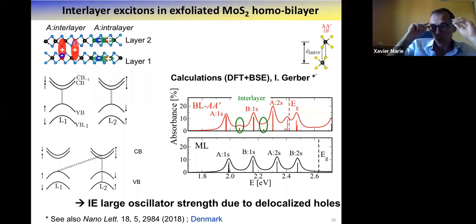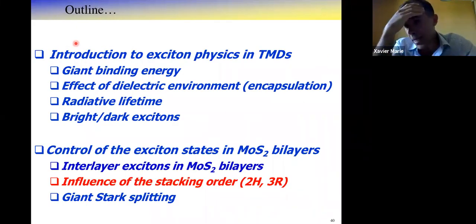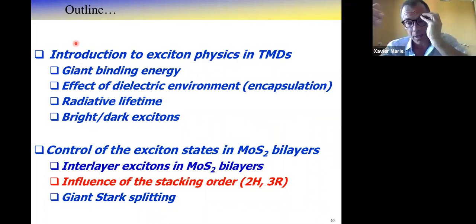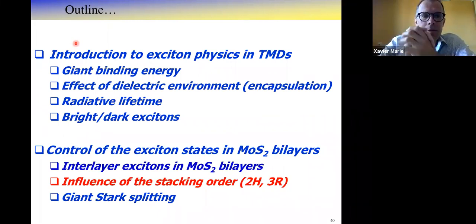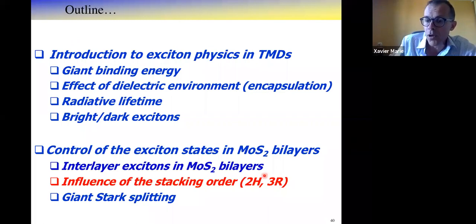And to confirm this, we tried a little bit to play with the symmetry and the stacking order. So again, not in a very fine way like all these Moiré results which are presented in this symposium, but in a very basic way, 0 degrees between the two layers and 180 degrees. So we will compare from an experimental point of view the interlayer exciton with a 2H stacking, the one I already showed, but also the 3R stacking.